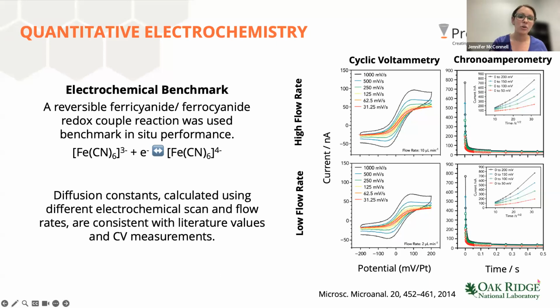And Oak Ridge, at Raymond Unocic's group at Oak Ridge, was one of the first to really jump on this with the Poseidon system using the model ferrocyanide redox couple. They found that the diffusion constants calculated using different electrochemical scan rates and flow rates were consistent with CV values in the literature. So we felt early on that quantitative electrochemistry is absolutely possible, even in a vessel that looks quite different than what you would typically use.